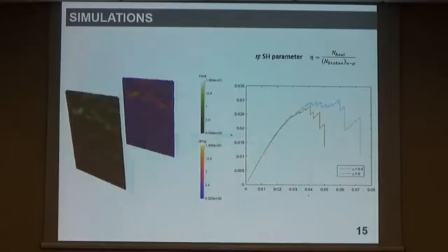And to end, we are performing some ongoing simulations on self-healing, which is an interesting property of biomaterials. Biomaterials are able to heal themselves when there is damage occurring. So this is quite early. Basically, we introduce a self-healing parameter, which is the number of healed bonds over the number of broken bonds at each step, and we want to see if structure can optimize the self-healing property of those materials.